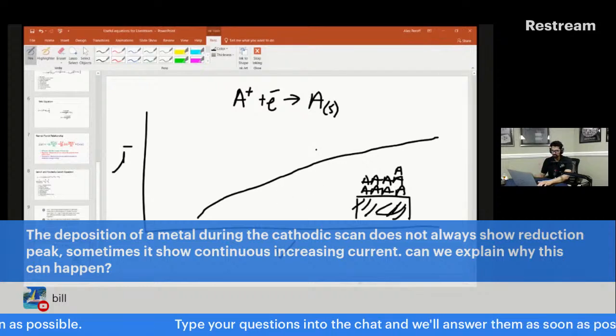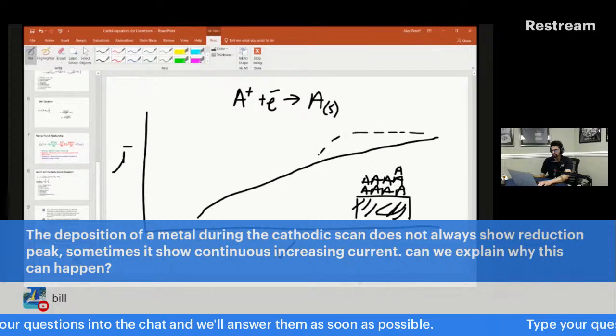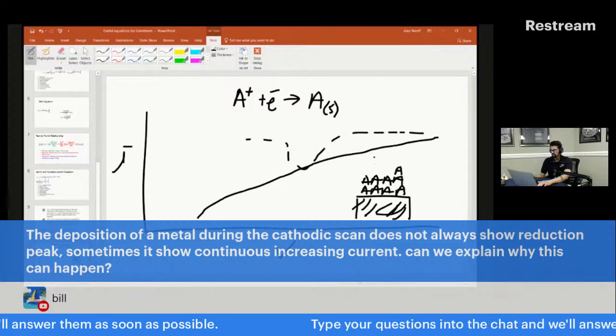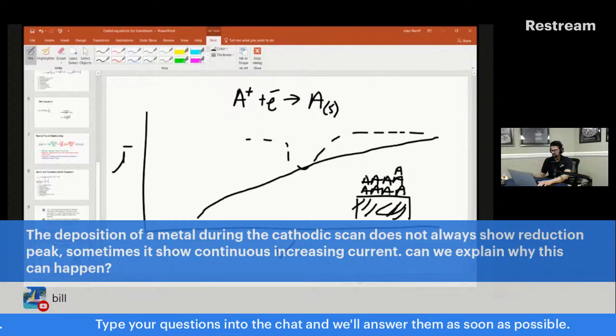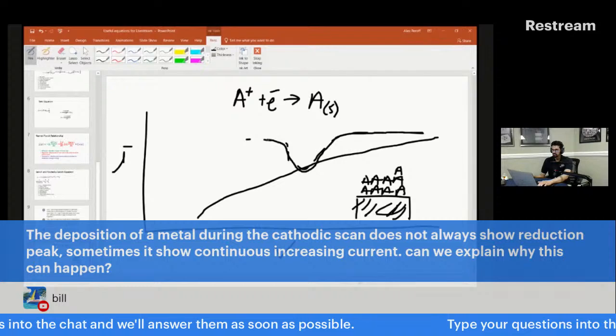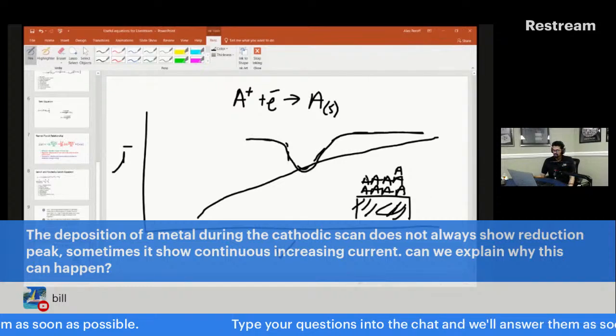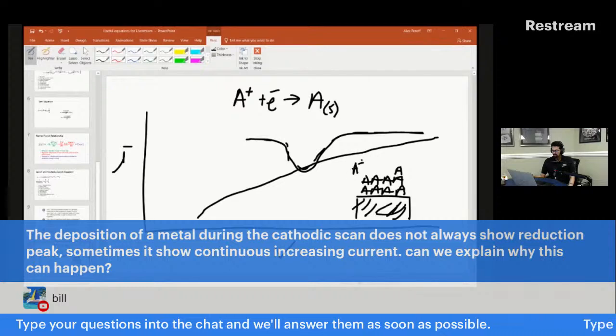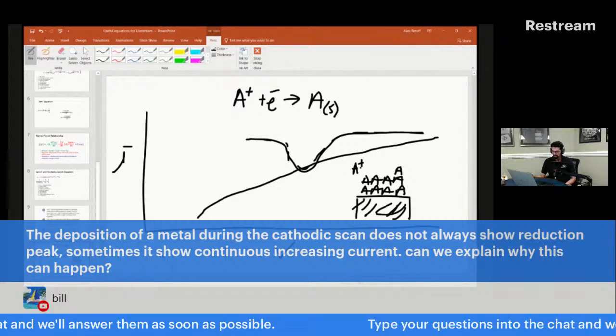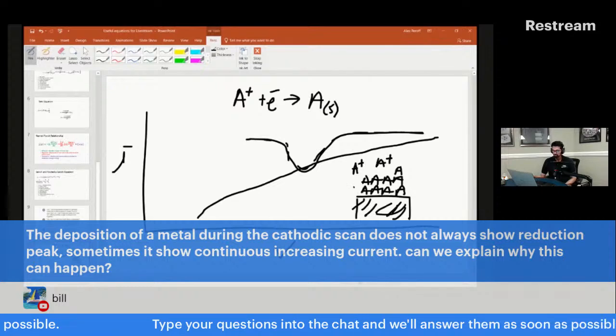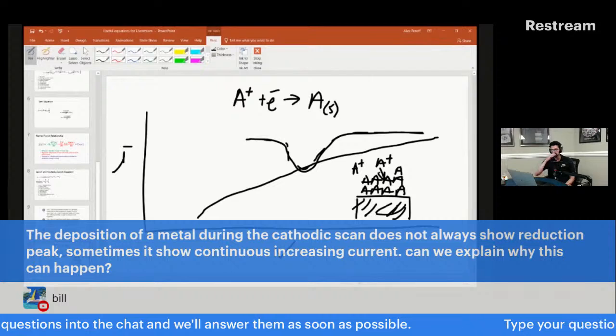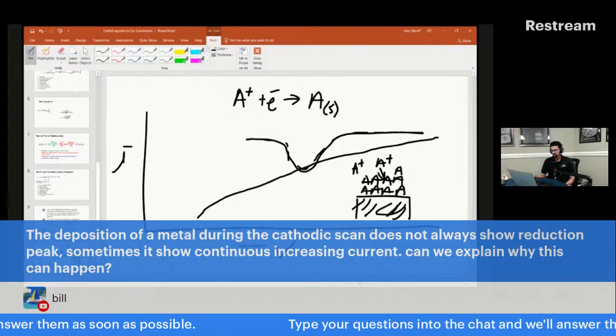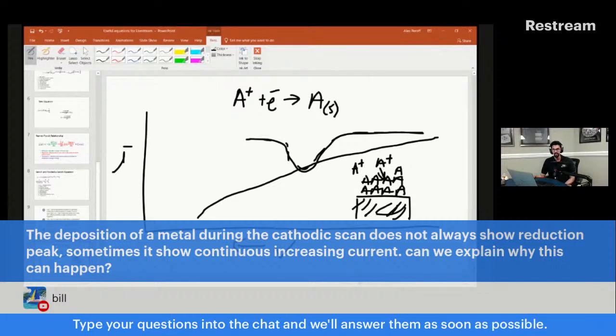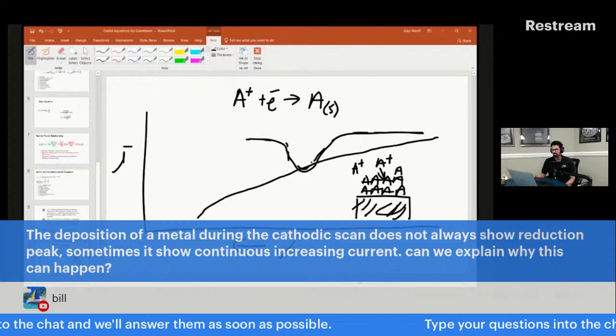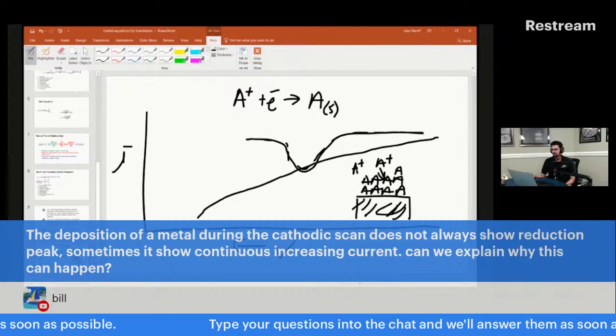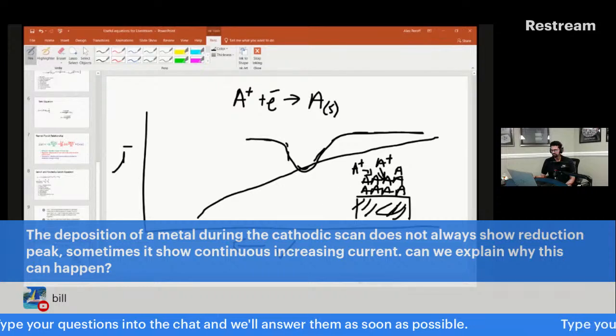And so normally, in normal electrochemistry, when you have a peak, it shows that the rate at which these A's are going on the surface is decreasing, and this peak always arises due to a mass transport limitation. But here there is no mass transport limitation. You generate some new A, that A disappears, and there's plenty of A plus in solution, which very easily moves to the surface. You are also making the reduction potential more and more negative. So kinetically, you're increasing the rate. You're providing more driving force to get these A's to reduce to A solid.